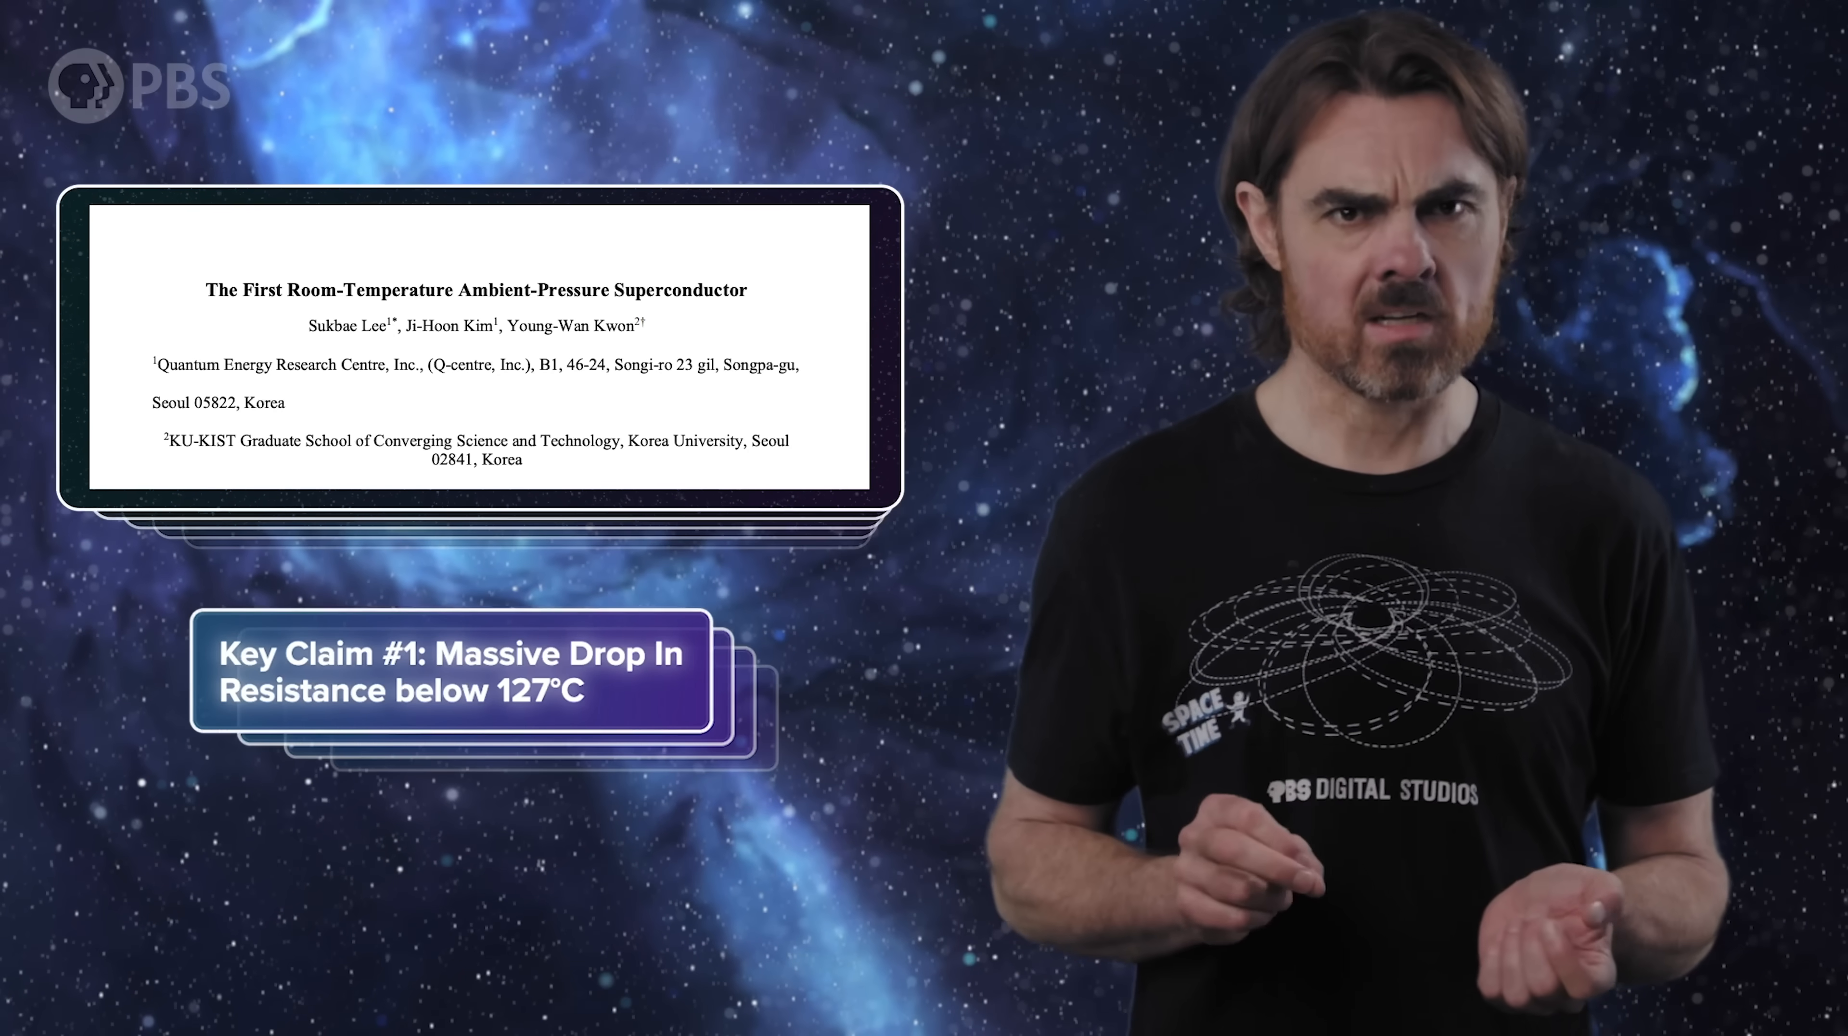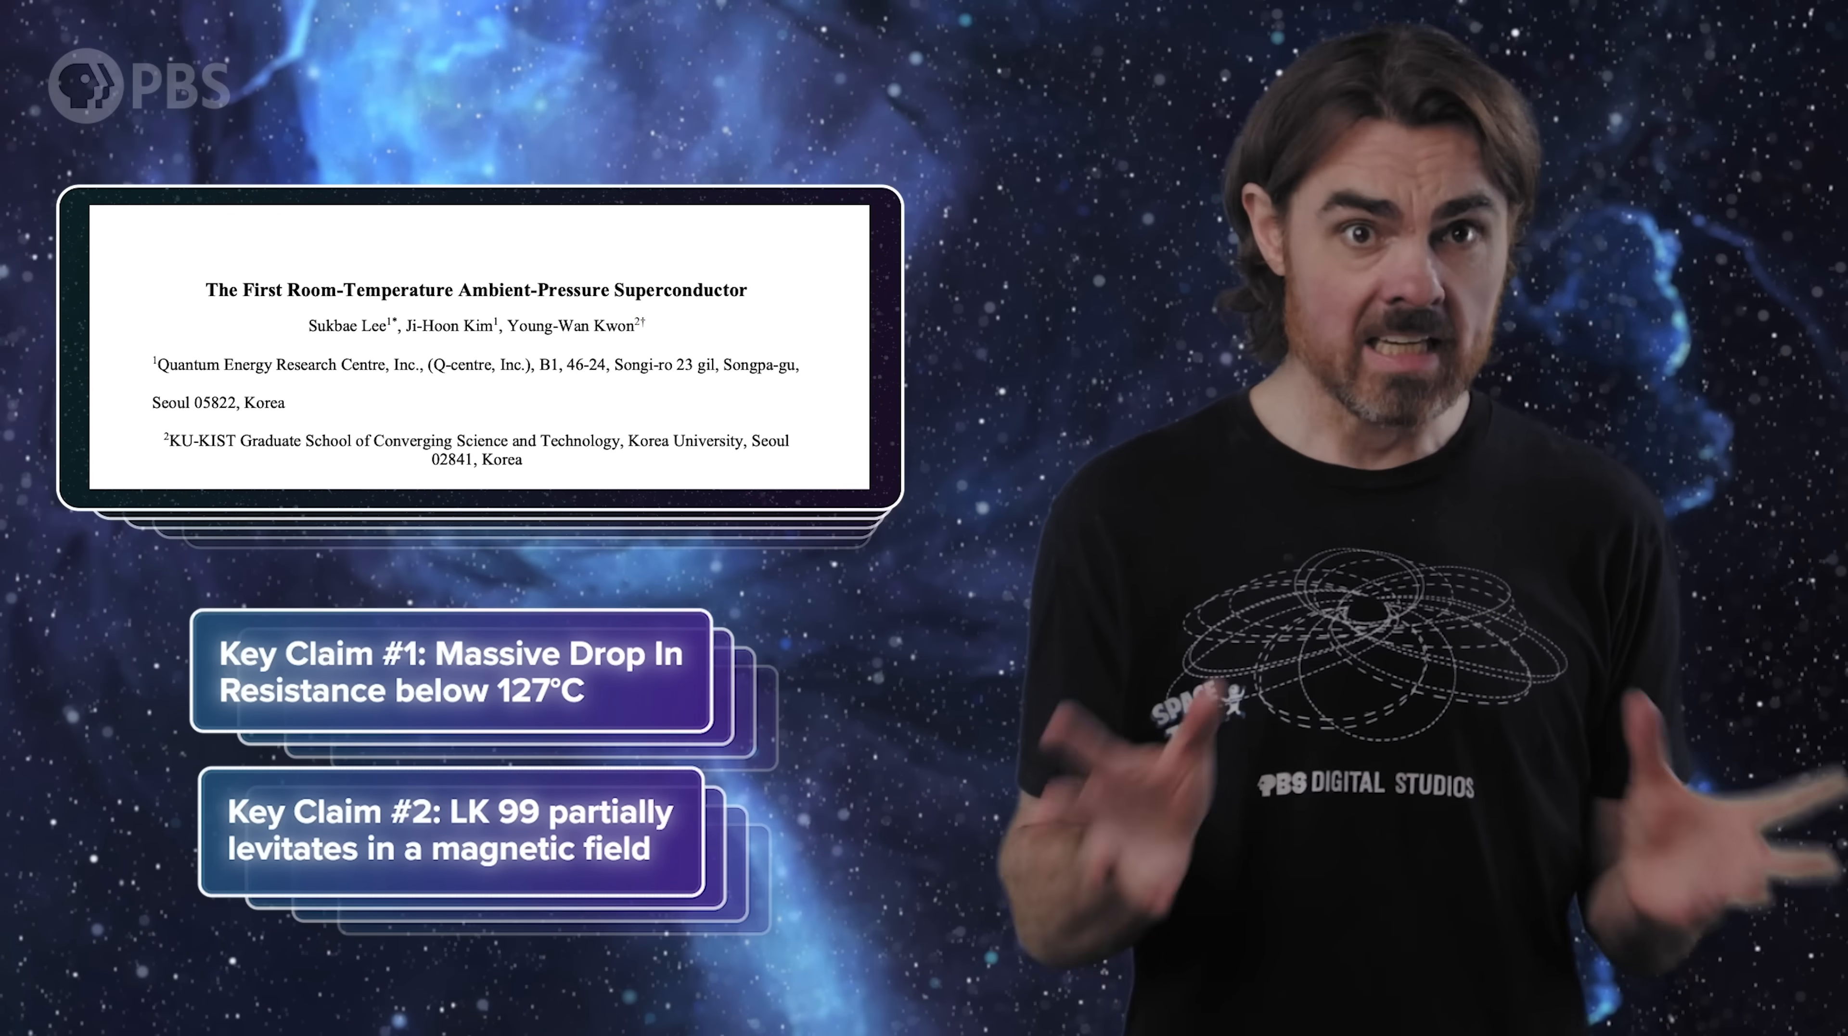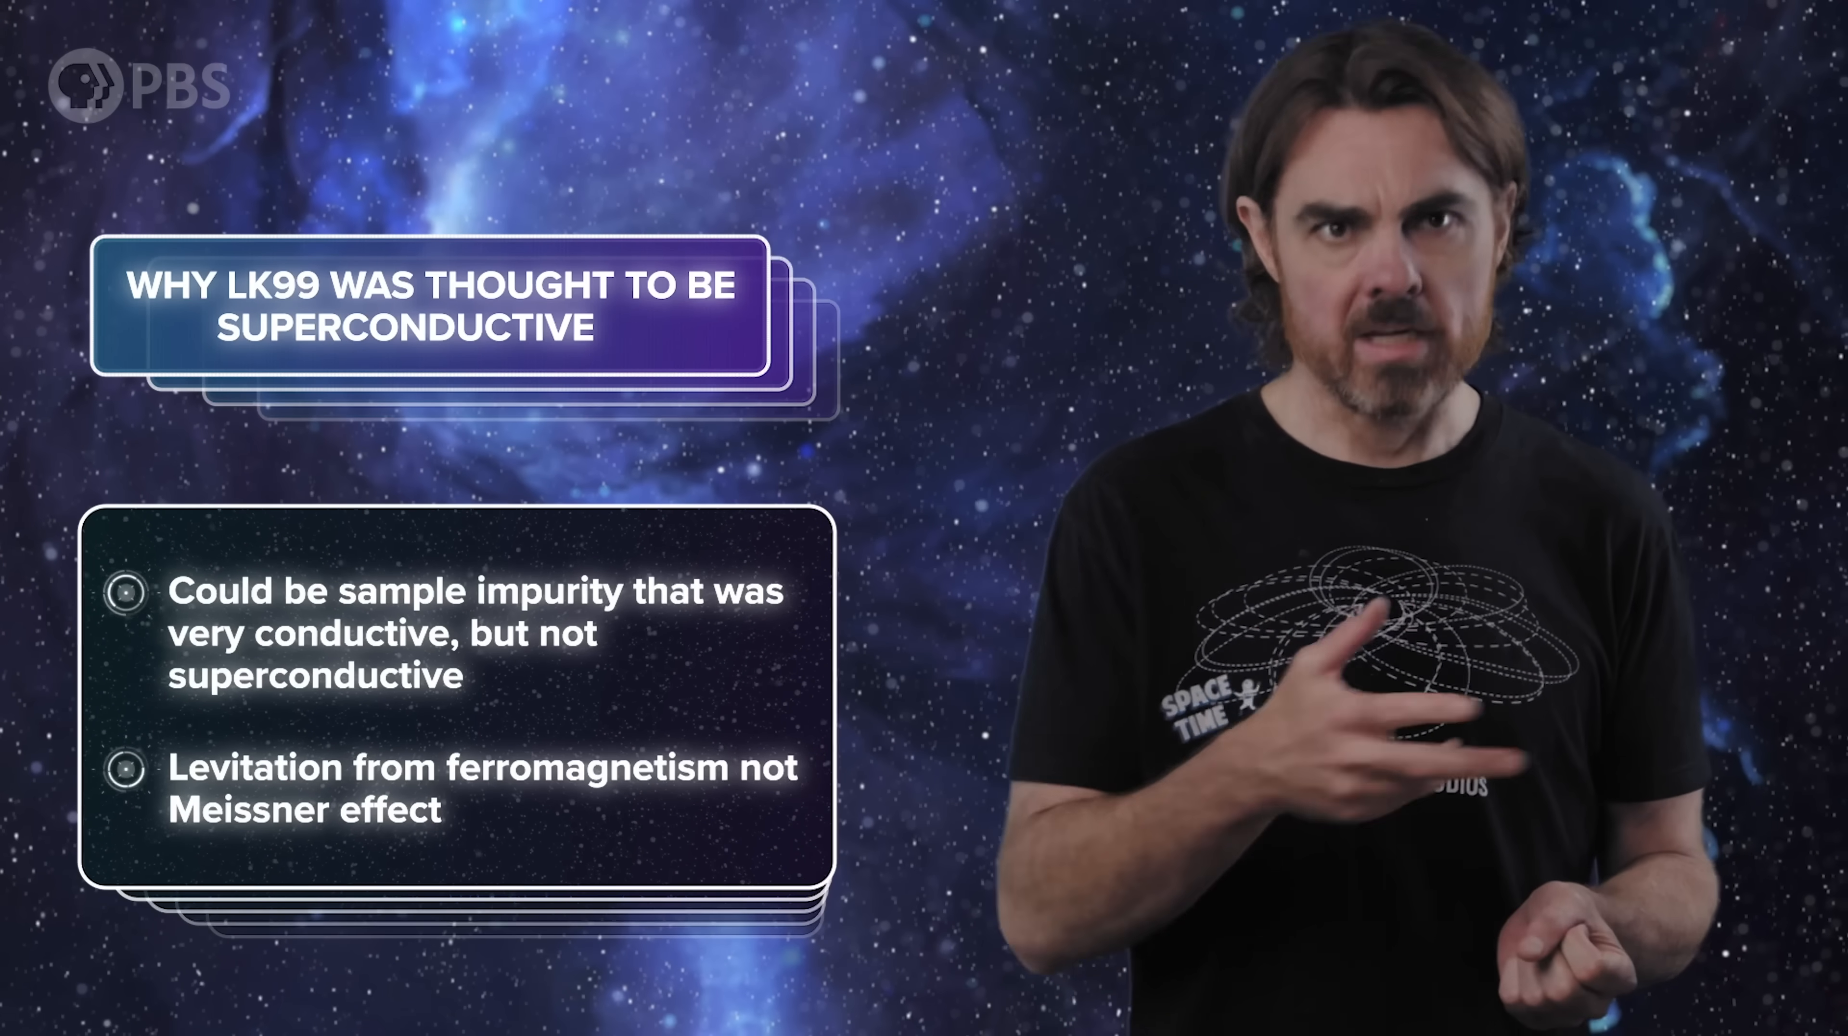Okay, so you and I now know quite a lot about superconductors. Maybe it's time to try to debunk the recent claim of this phenomenon in LK99. So the team claimed a massive drop in resistance below a temperature of 127 celsius, so actually quite a bit hotter than room temperature. And the material also appeared to partially levitate in a magnetic field. But since then, a number of teams have synthesized the same material and report no evidence of superconductivity. Speculations about why the original team thought otherwise include that their sample had an impurity that made it just very conductive, regular conductive, but not superconductive. And that the levitation was probably just regular ferromagnetism, not the Meissner effect.